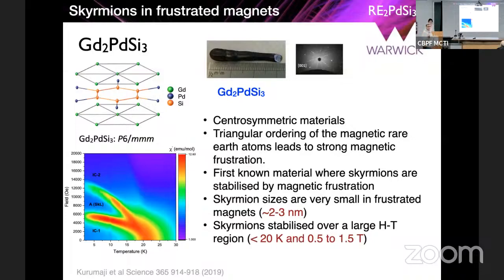Other question? What kind of adaptation have you done to the floating zone furnace for this intermetallic? So we just have the ability to evacuate the chamber, so it's free of any oxygen. Apart from that, there's not a lot that we've done. You need to be able to achieve the temperatures at which these materials melt. Some of these materials melt at temperatures close to 2000. So you need to be able to achieve that temperature and also work in a completely oxygen-free atmosphere. So you need to have it very airtight and be able to pump it down to a very high vacuum so that you can backfill it with high purity argon and then work with the system.